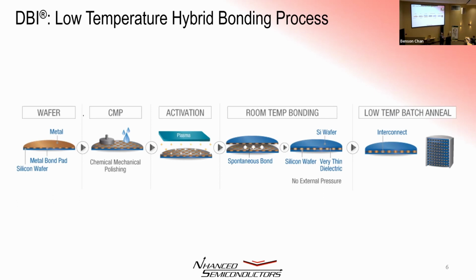You get a room temperature van der Waals bond. The good news is that they stick and they don't fall apart. The better news is that we can look at it and see how good the bond was. And if it's not good, we can take them back apart, clean up the wafers, do a little repolish, put them back together again. That bond is not permanent until we do the anneal.